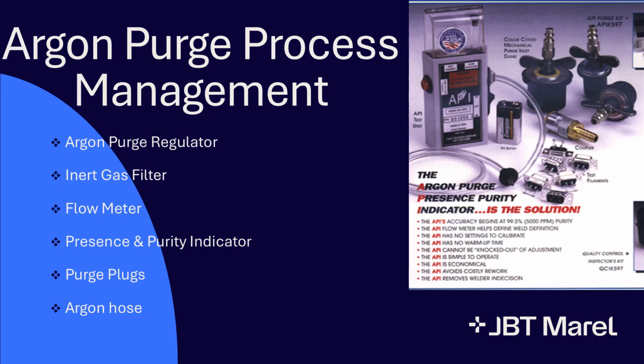Argon hoses is another big thing. You're going to want to make sure that it's compatible with the gas that you're using. And the past few years, we've had an issue where we have complete purge, or so we thought we had complete purge, and we're still getting these color variations. Now, one thing that can contribute to that is the humidity in your room. So making a temperature controlled and humidity controlled environment is crucial, but also the means of transportation in the line.